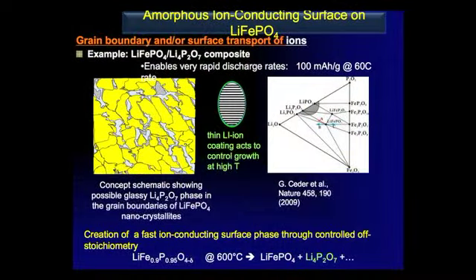And then moving along to 2004, we considered a different sort of process, which is effectively to use carbothermal reduction to convert the carbon to a combination of FeP and a metallic iron phosphocarbon glass. This is a metallic glass which has a conductivity similar to that of iron phosphide. So this is a cartoon of an actual TEM image where we did careful analysis of the grain boundaries and learned this is the iron phosphate particle itself shown in yellow, and the grain boundaries shown in gray and blue contain this mixture of substances. And it's kind of complicated to go through in this talk, so I refer you to our paper.